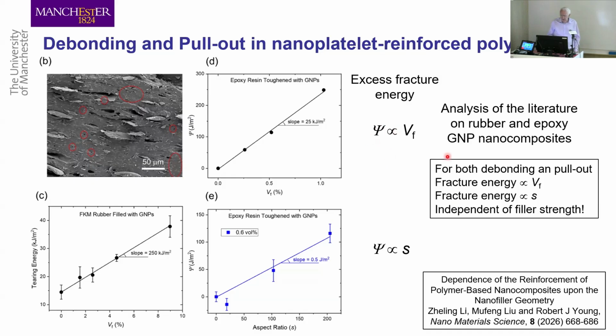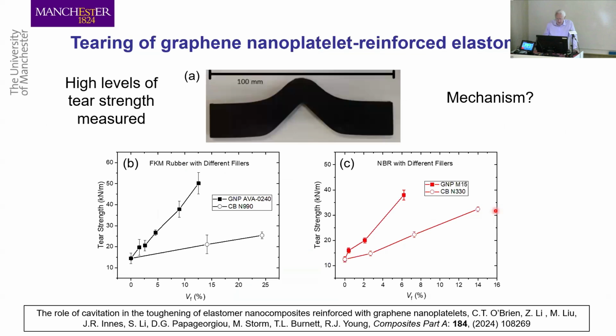However, it's independent of the filler strength. So again, the strength doesn't matter. It's 100 times stronger than steel or whatever, but doesn't matter. You never achieve that. You never see that. You don't need it. However, when you go through the details of these analyses, you find that you get very high levels of fracture energy, tear strength.